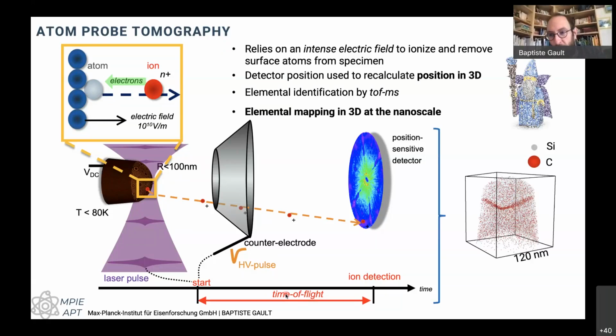And then I'll tell you a little bit about the magic that we use to go from this information in 2 dimensions plus the time of flight into a typical atom probe data set that would be a point cloud like this, where every point is one ion that was detected. And the color we associate to a specific element. So for example, this is silicon for photovoltaic applications. There's a grain boundary here that is faceted, and we can see carbon segregated at the 2 facets, and primarily here at the junction between the 2 facets. So this is the type of information we can get from atom probe that would be really hard to get from any other technique.